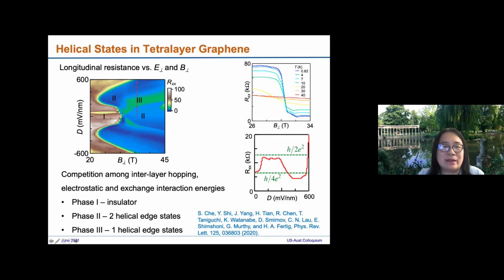We can also take a line cut here. This shows we have phase two with 4 times the conductance quantum, and then phase three with 2 times the conductance quantum. This can be a little bit involved, combining both the single-particle calculation and also interaction effects, but phases 1, 2, and 3 have a different number of edge states: 0, 2, and 1 edge states. And again, we can change the number of helical edge states by electric field and magnetic field.